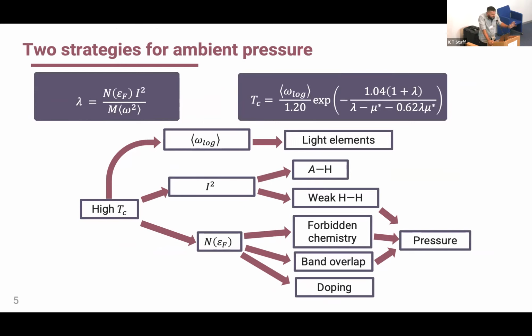So we start from the left, that is what we want, the high TC. And we need these three ingredients: the large omega log, the large electron-phonon matrix element, and the large density of states. Now, with hydrides, the large phonon frequencies, we have them for free. We don't have to worry about them.